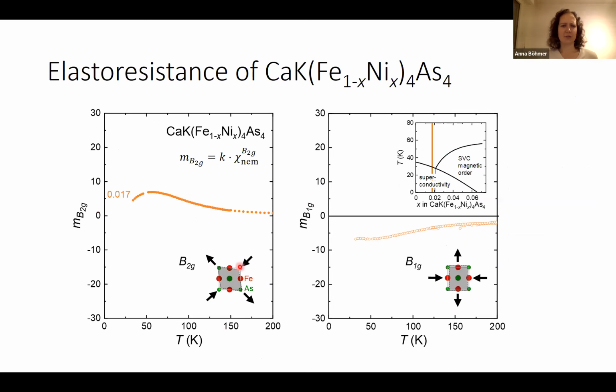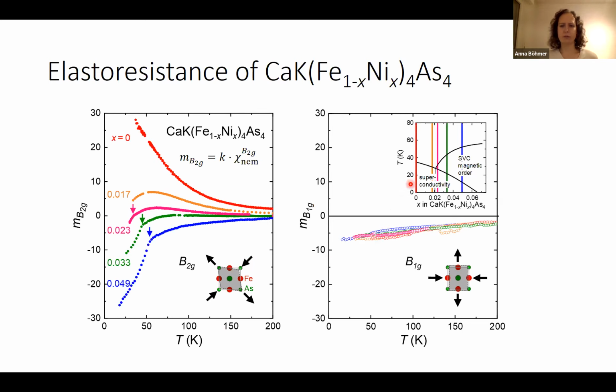So when I do this, here for the one example, the B2g and the B1g elastoresistance coefficients related to these different strains, and that's the doping evolution all over the phase diagram. First of all, the B1g doesn't evolve at all. So it does not depend on the composition. It's unaffected by whatever drives this phase diagram. So there's no interactions there, so we will not look at this one. On the other hand, the B2g, that's quite interesting. There is a very pronounced evolution of behavior here, different temperature dependencies, different signs. So let's take a look at that.